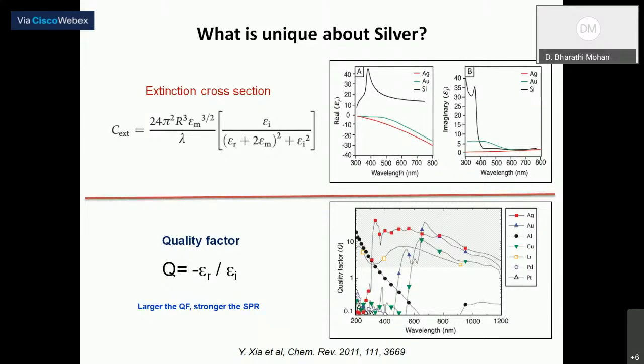Silver is one of the very prominent materials in the field of nanoplasmonics because it supports SPR in the entire visible range to the near IR range. SPR depends on the dielectric function. The extinction cross section equation is derived from Mie theory. For any spherical particle, it is given as 24π²r³ε_m^(3/2)/λ times ε_i divided by (ε_r + 2ε_m) the whole squared plus ε_i squared.